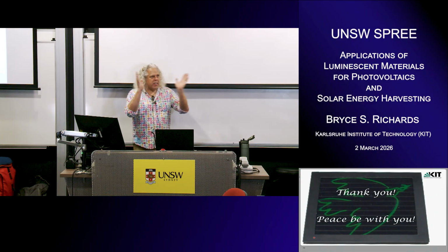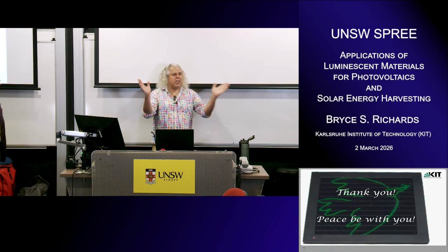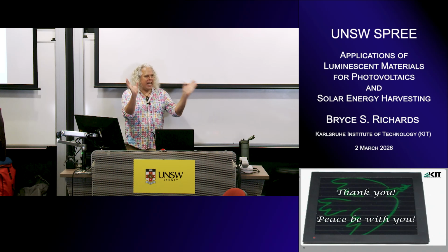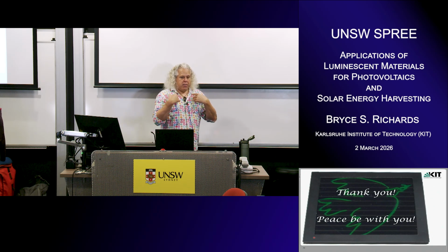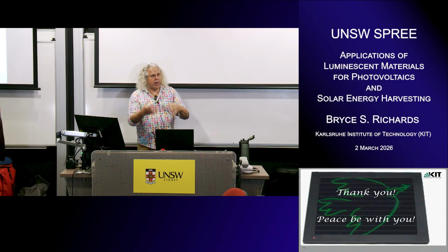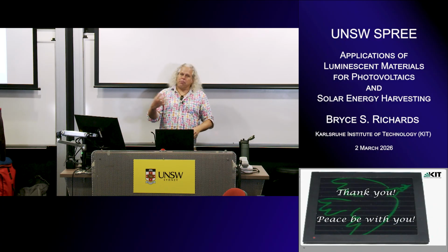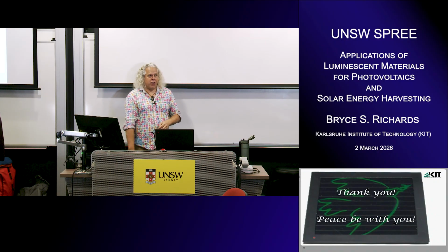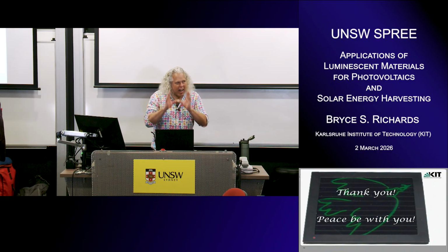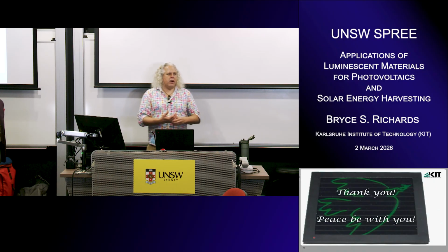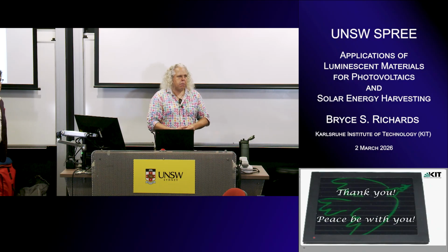So you've got a silicon CCD that's really operating across its whole range and really on the edges of its spectrum. I can't speak for Gamelin's group, but I know from our experience, sometimes when we get a stray result, we say we should check the calibration on that, and it matters. Yeah, so the calibration of the spectrometer is key in the whole quantum yield measurement.